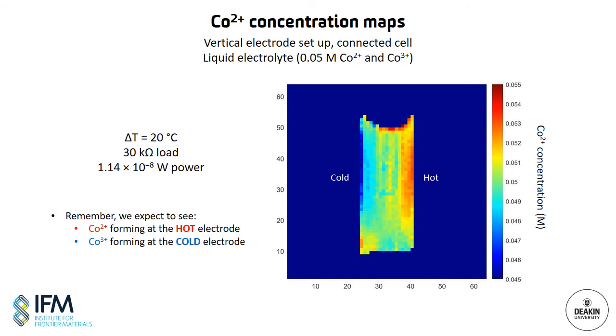The reason for this was to not have too much convection occurring inside the cell, which can potentially lead to artifacts and image distortions. Nonetheless, there will be some convection occurring in this cell. And one avenue we're pursuing is to use velocity mapping experiments to measure the convection, but I won't show any data on that today. So this particular image was obtained from a cell operating under a 30 kiloohm load, and